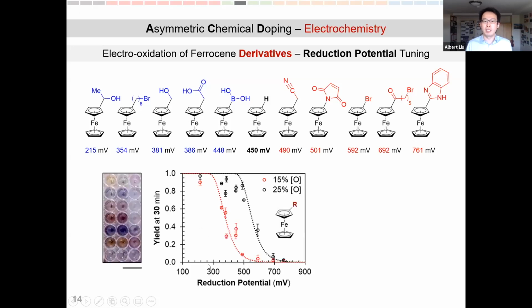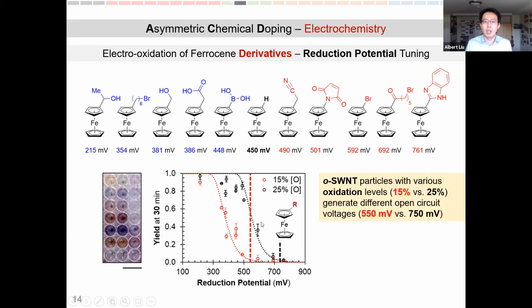So here, we take different particles and put them into a 96-well plate and just watch this reaction go as a function of time. If you plot the reactivity as a function of the reduction potential of all these different ferrocene derivatives, we see higher reactivity for the derivatives that have lower reduction potential, in accordance with an electrochemical reaction mechanism. One thing I will mention is that we have two sets of data. Black ones are for the more oxidized single-walled carbon nanotube Janus particles, whereas the red ones are for less oxidized particles. As we know previously, more oxidized carbon nanotubes generate higher open circuit voltage, hence having higher overpotential to drive this electrochemical process, therefore achieving faster reaction rate.